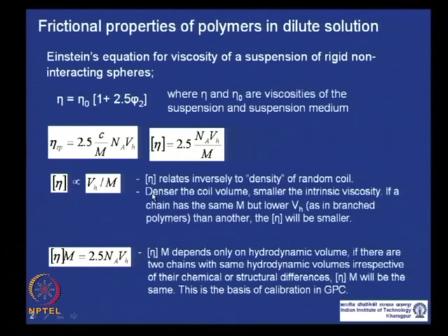Now, another piece of information this expression gives is that the term intrinsic viscosity multiplied by the molecular weight depends only on the volume of the polymer coil in solution. So, intrinsic viscosity alone does not depend only on the volume. It depends on the inverse of the density.